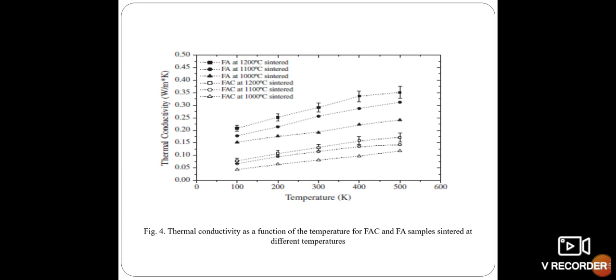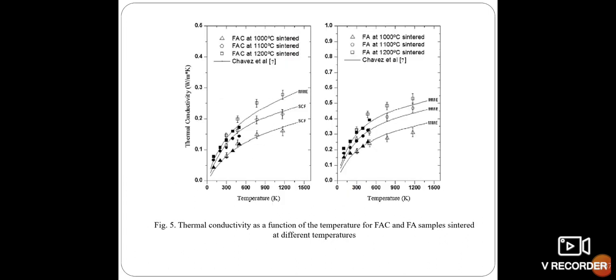This is a representation for the thermal conductivity as a function of the temperature for FAC and FA samples sintered at different temperature levels. And the next one represents the thermal conductivity as a function of temperature for FAC and FA samples sintered at different temperatures. From this, FAC coatings show lower thermal conductivity than the FA coatings due to the hollow nature of the cenospheres, which limits the heat transfer.